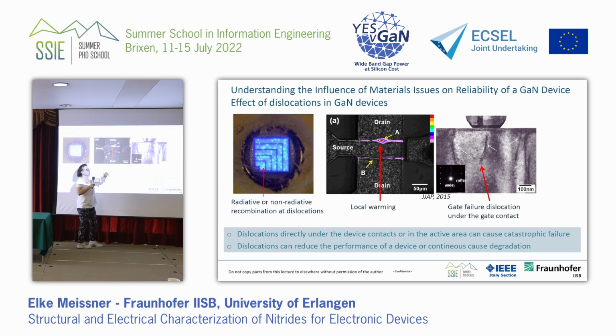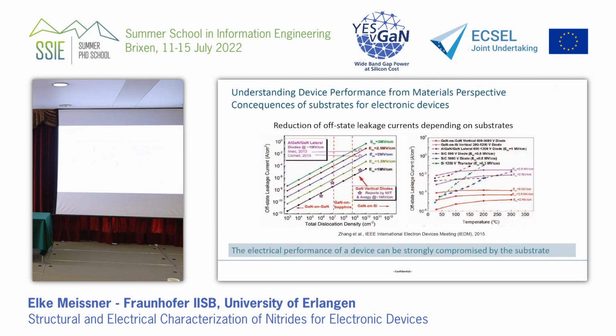This is what we do, so we see such type of pictures, we say, okay, this is a problematic area, and now we look directly inside what there is with all the knowledge that we have from crystal growth until defects on different scale. And here, for example, you see, but this is a lucky case, I would say, if you grab it in preparation like this, you see directly underneath a gate. In this example, there is a dislocation where you say, okay, this dislocation or dislocation bundle had caused the gate failure. This is a very direct evidence that you cannot achieve all the time. I will show you examples where you see that only by statistical means you can really achieve that. So dislocations that are directly under the contacts or directly in these very active areas like in the gate area, they always cause to the majority catastrophic failure of the device, whereas other dislocations can also cause gradually loss of performance. And this all is not so easy to be investigated.